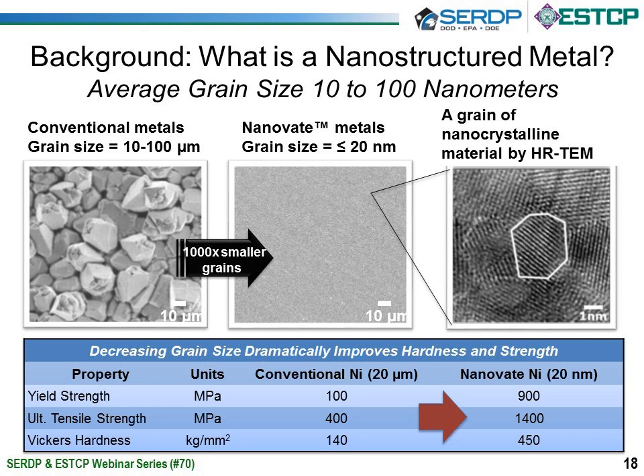And by doing so, you get very interesting property changes, specifically as it relates to the hardness and the strength of the material. As an example, going from a conventional nickel with a 20 micron grain size to a nanocrystalline nickel with a 20 nanometer grain size, you get an increase in yield strength from about 100 megapascals to about 900 megapascals. And similarly, you get an increase in hardness from 140 to about 450 Vickers hardness. So you see tremendous property changes when you just simply reduce the grain size of the material.